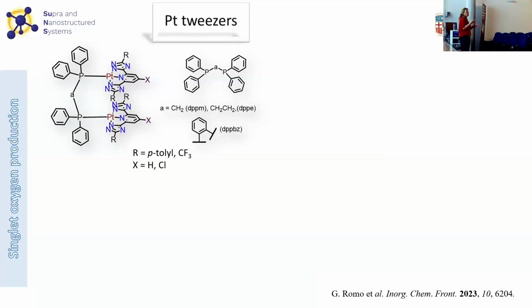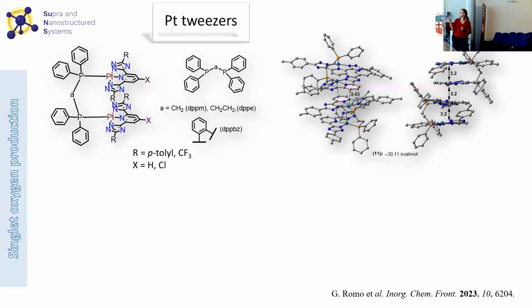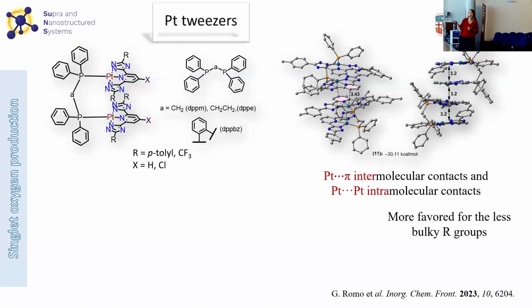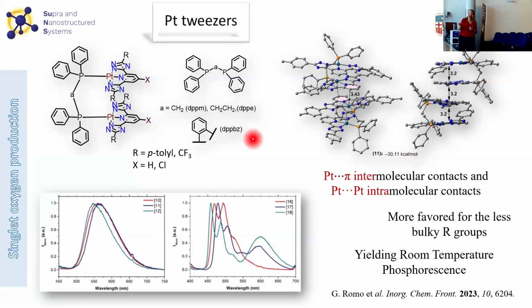So we are focused in the last years on trying to have these structure-activity relationships, trying to modify the samples a little bit to get more information and at the end be able to predict how favorable the singlet oxygen generation should be with a determined chemical structure. So in these cases, with these platinum tweezers, the theoretical calculation suggests that there are some platinum-pi and platinum-platinum interactions that are more favored when these R groups are less bulky, as expected, yielding room temperature phosphorescence that can be observed in this spectra.